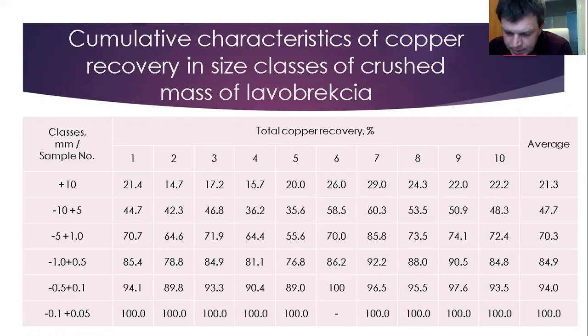of enrichment. Enrichment equipment operates at a certain lower limit of feed size. For example, grades plus 0.5 millimeters, where copper recovery is 85%, are easily enriched by gravity methods, for example jigging; you can see more at the end of my article about this.